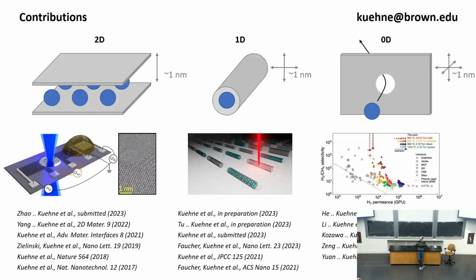So that also plays into the actual thermodynamics, whether it's open or closed at the end. In the case where it's open, you still have this equilibrium between an outside reservoir and basically a local gas phase that you create. It's like a vapor phase. You have a gradient in temperature that you create, but you don't measure the kinetics. We didn't measure. You basically create it very fast thermally. The system gets to a steady state very quickly.